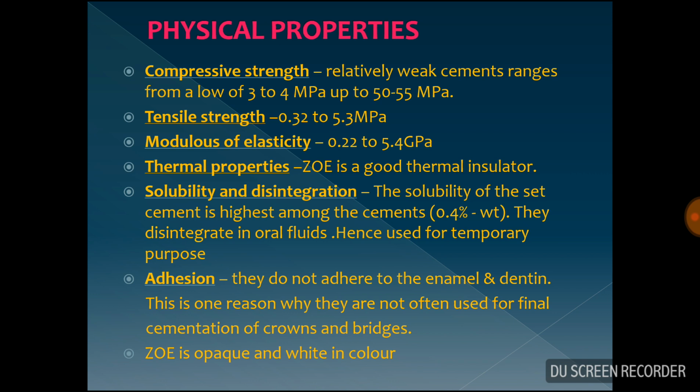Eugenol can leach out from the material, leading to hydrolysis and disintegration of the cement. Hence, these cements are mainly for temporary usage. Adhesion: they do not adhere to the enamel and dentin. This is one of the reasons why they are not often used for final cementation of crowns and bridges.